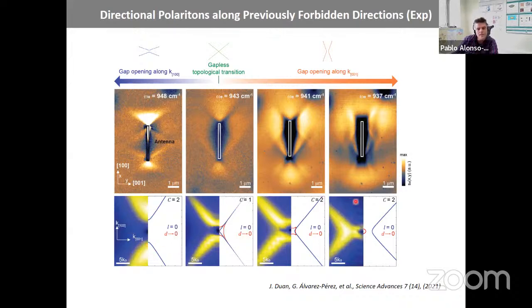We saw that there is always this kind of transition, this topological transition, optical topological transitions, where exotic optical phenomena occur. In this case, it is this reorientation and this propagation along a forbidden direction. And now, in the next few minutes, I want to explain another one that will give rise to this wave guiding. Okay, but this is the first case of topological polaritons. The gap was open along this 1, 0, 0 direction, then it is a gapless curve, and then it's open along the other direction.